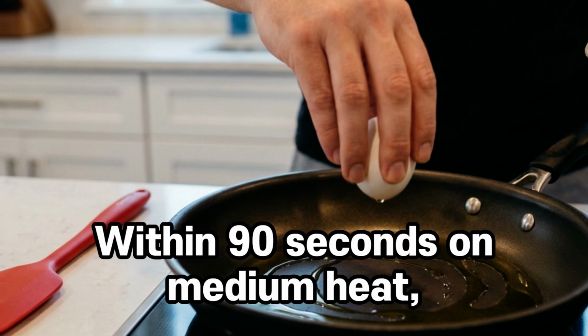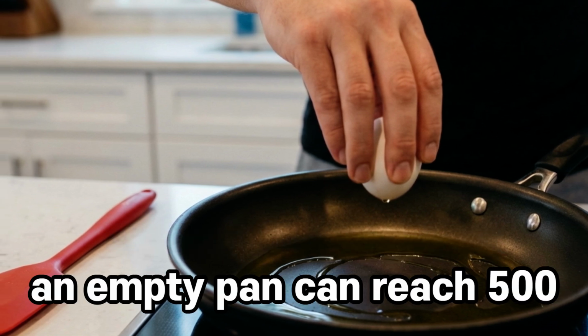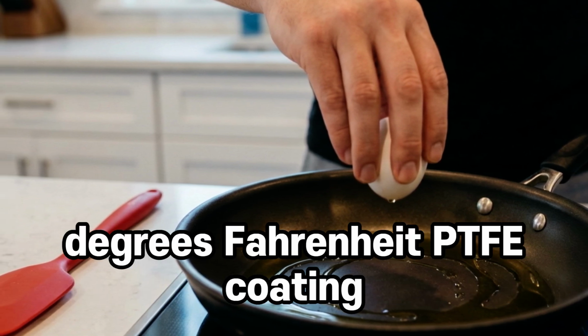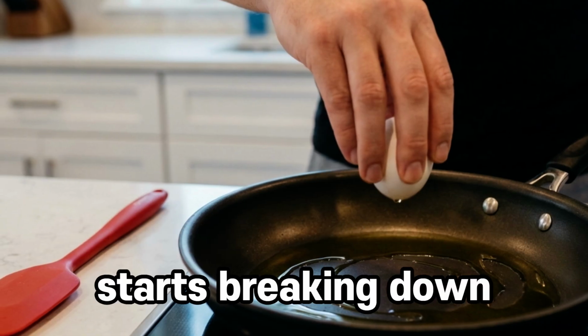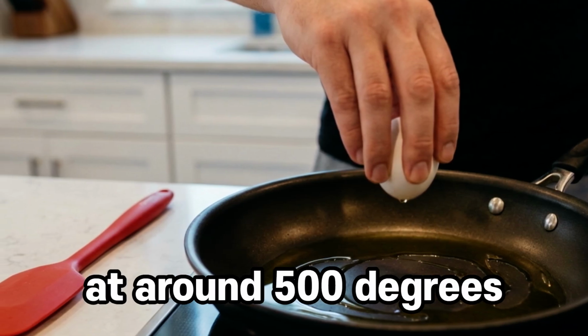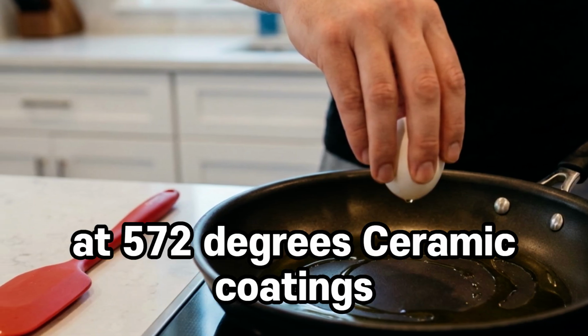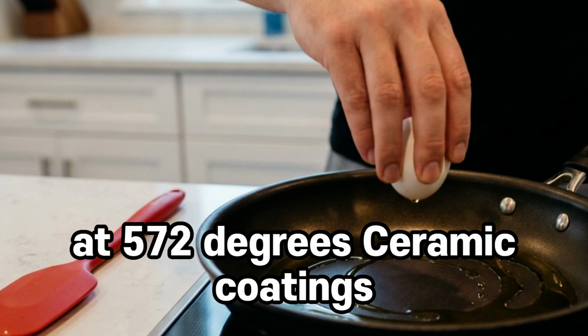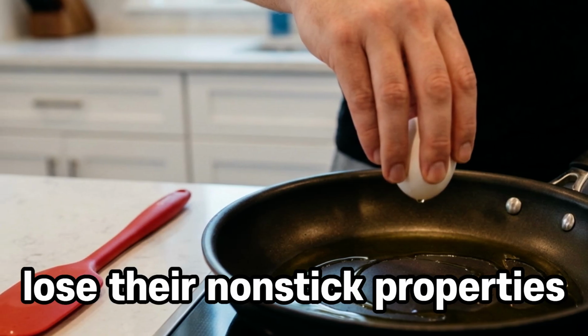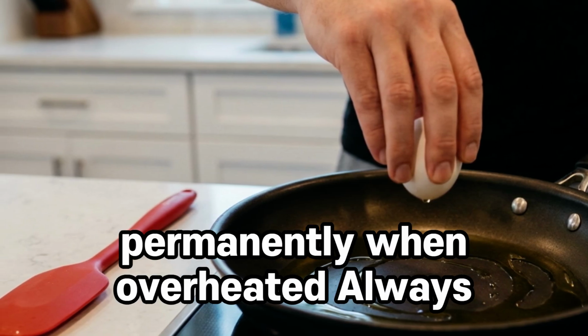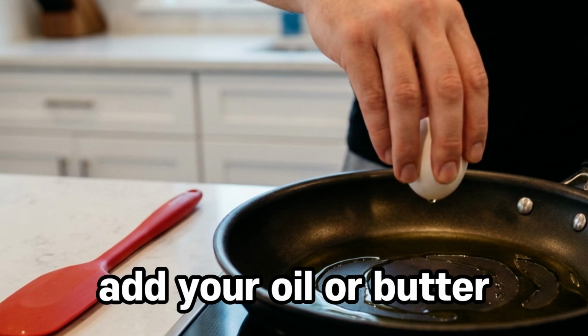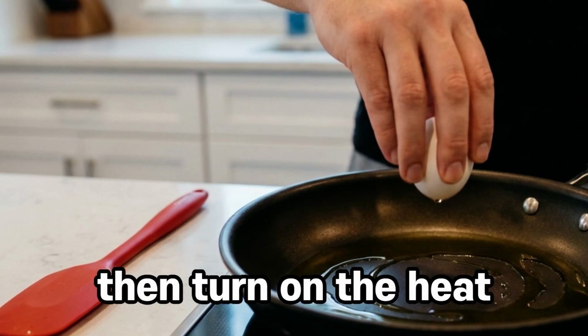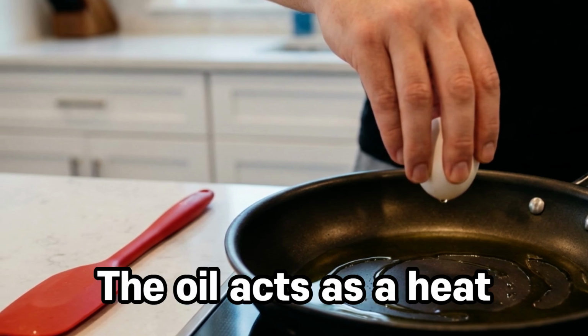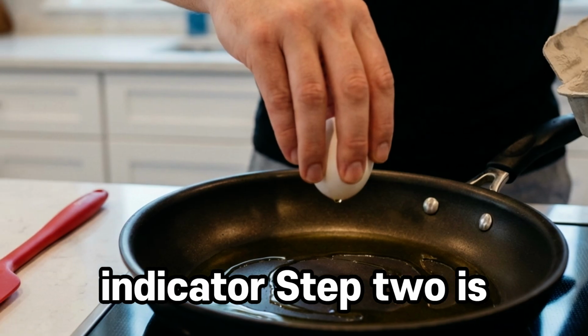Within 90 seconds on medium heat, an empty pan can reach 500 degrees Fahrenheit. PTFE coating starts breaking down at around 500 degrees and releases toxic fumes at 572 degrees. Ceramic coatings lose their nonstick properties permanently when overheated. Always add your oil or butter to a cold pan first, then turn on the heat. The oil acts as a heat buffer and temperature indicator.